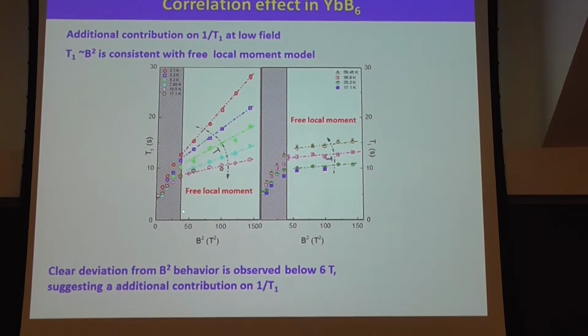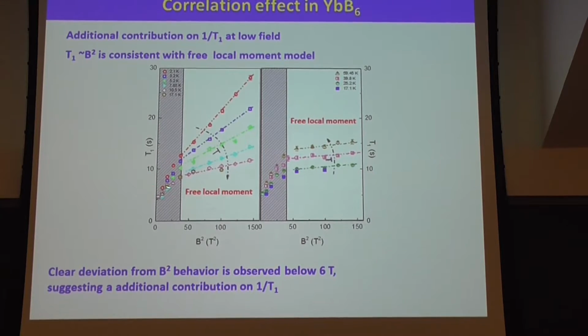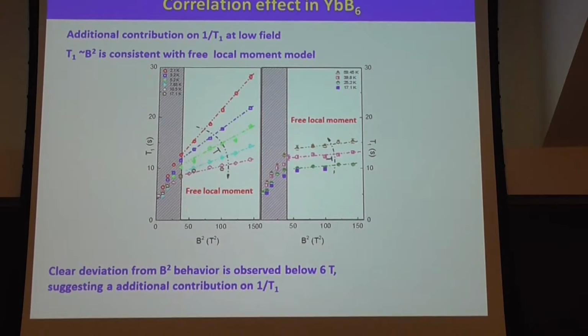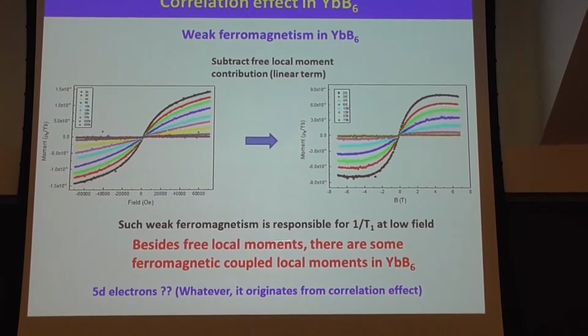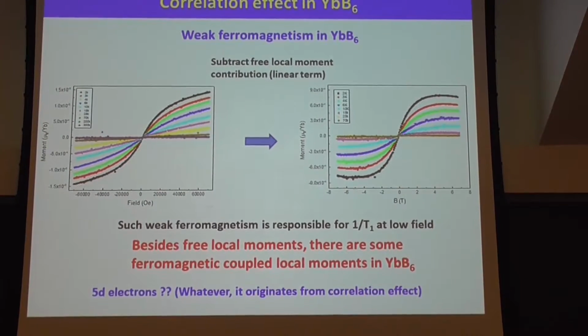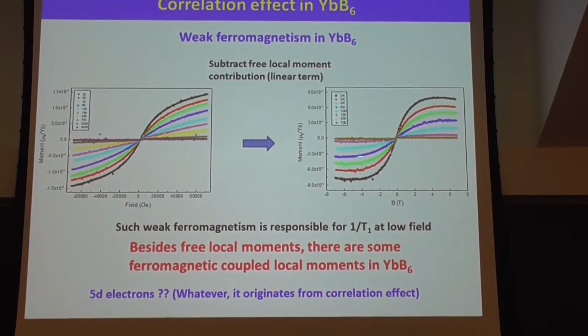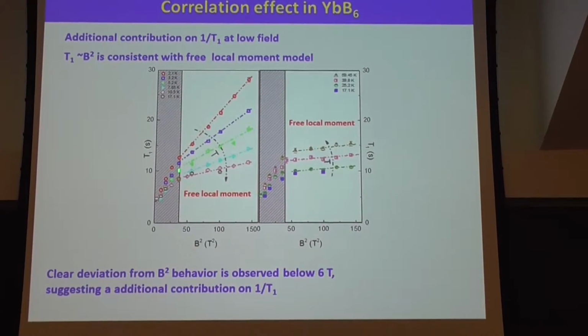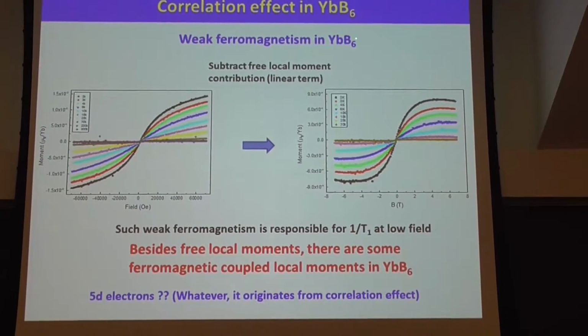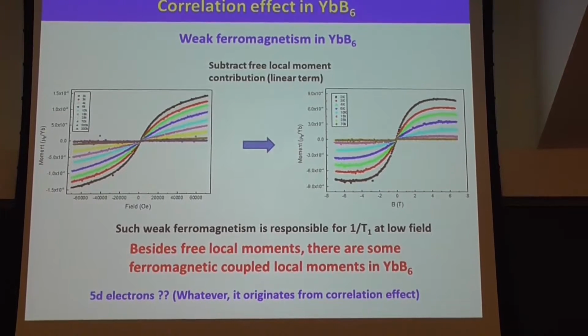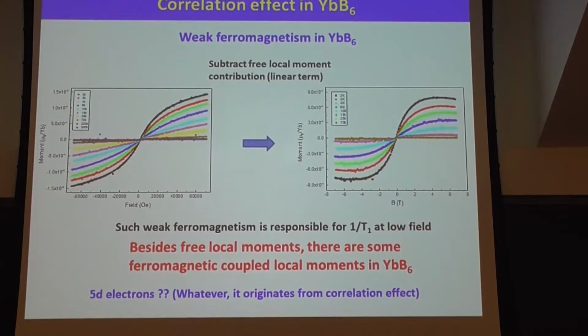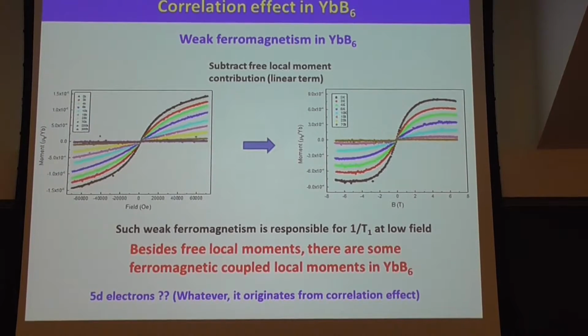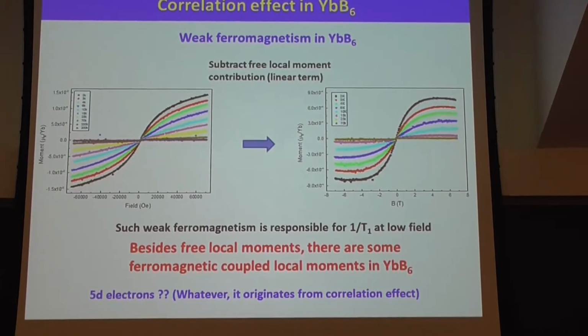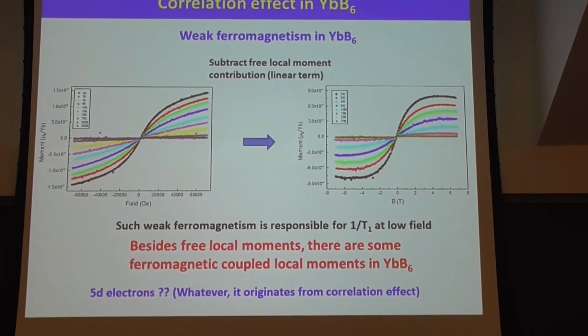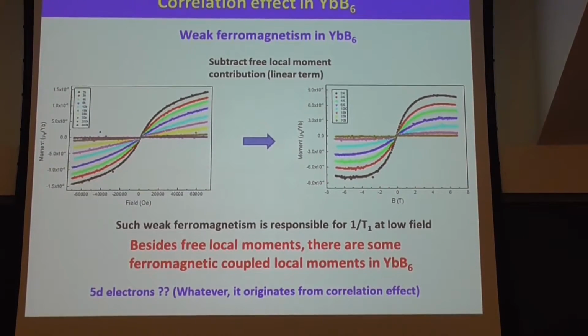But below this temperature, something is different. We found later, from the susceptibility measurement, that below this 40 Kelvin, this temperature shows ferromagnetism in this material. So for Ytterbium hexaboride, above 40 Kelvin there are some free local moments, and below this temperature, some correlation gives the ferromagnetic order.